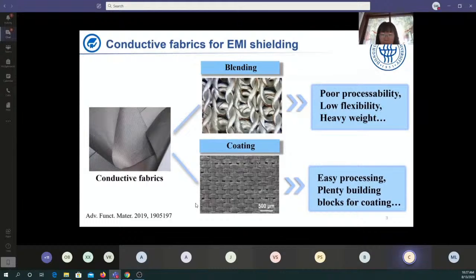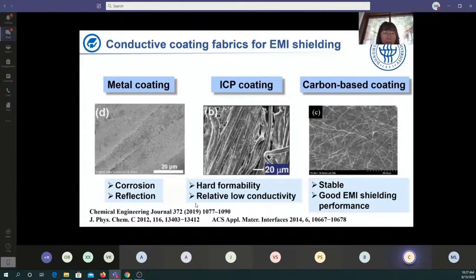Another approach is coating. This method uses conductive composite coated on the commercial fabrics. This process is easy and has plenty of building blocks for coatings. There are mainly three kinds of materials for coating. The first is metal coating. This kind of coating always uses nanowires or nanoparticles of metals to deposit on the fabrics. This kind of coating is easy to corrode and it reflects the electromagnetic wave.